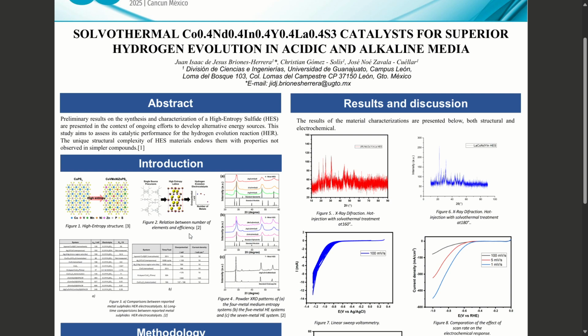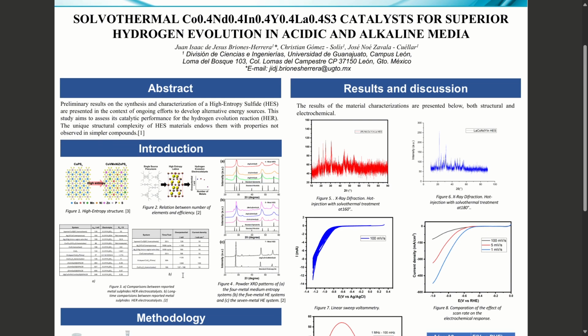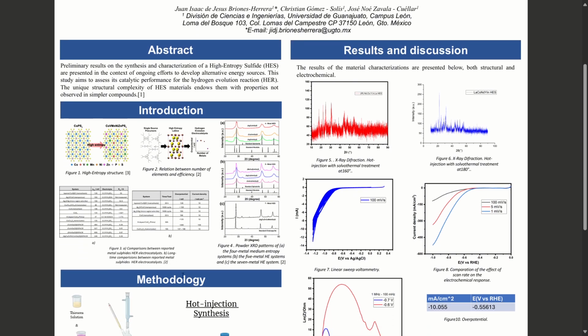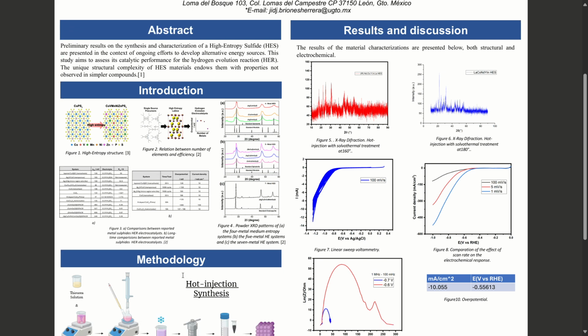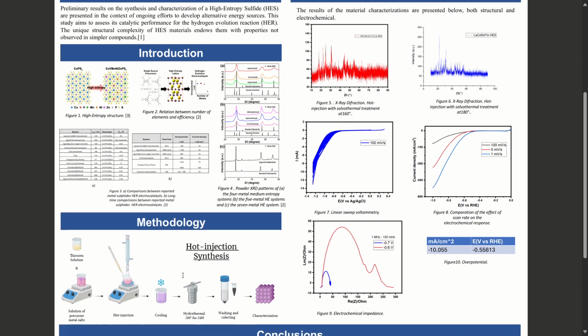In this project, we focus on synthesizing a high-entropy sulfide catalyst with the composition of cobalt, neodymium, indium, yttrium, and lanthanum. The synthesis was carried out using a solvothermal method, which is advantageous because it allows us to control reaction temperature, time, and solvent environment to tune the morphology and crystallinity of our product.